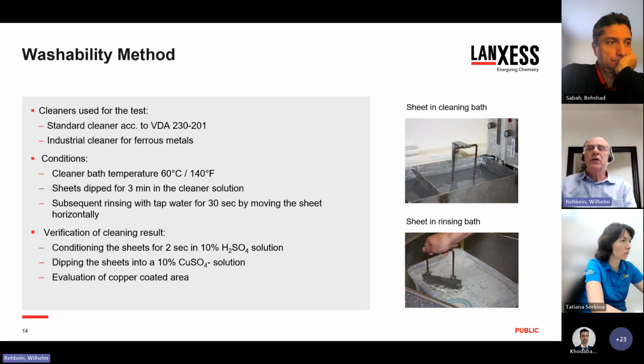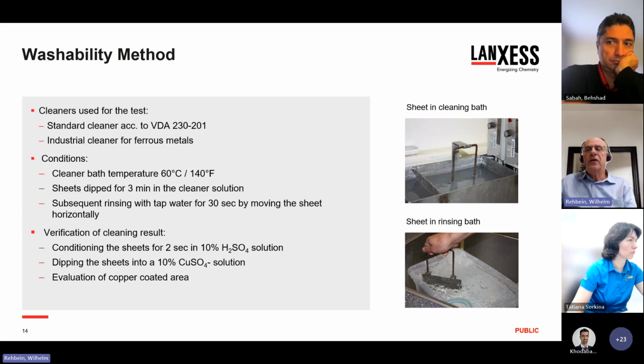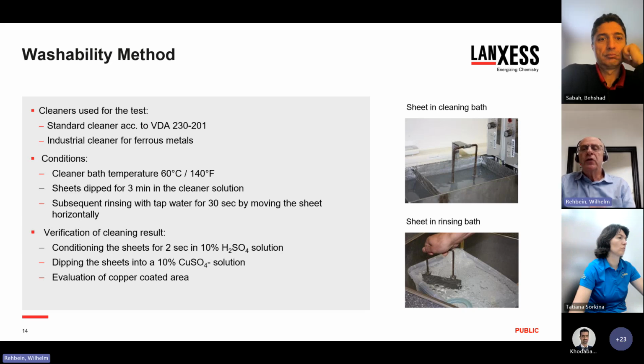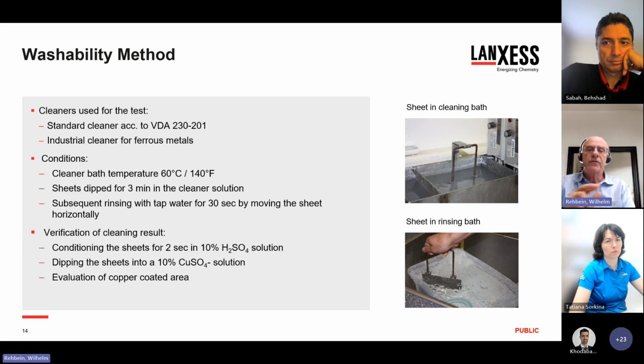So the sheets, which were covered with a dry rust preventive film, were dipped for 3 minutes in the different cleaner solutions. They had a temperature of 60 degrees Celsius. After that, we rinsed them with tap water for 30 seconds. And for better verification of the cleaning test result, we conditioned the clean steel plates by dipping them into a copper sulfate solution. So all the surface areas on the steel sheets which were perfectly clean were then covered with a thin copper coating.